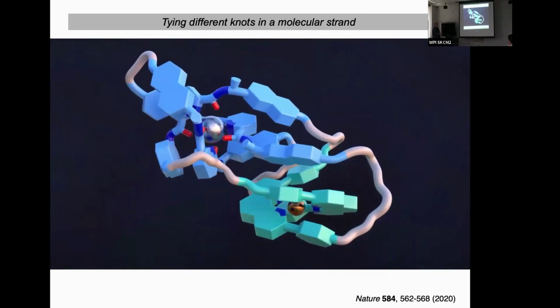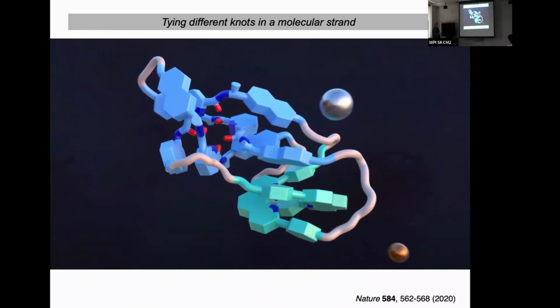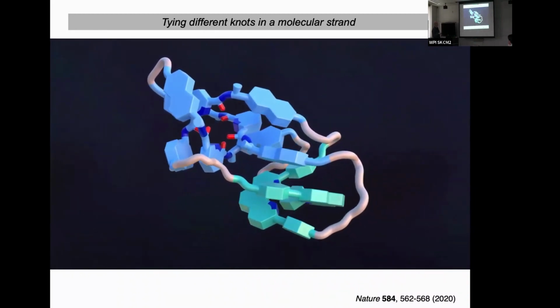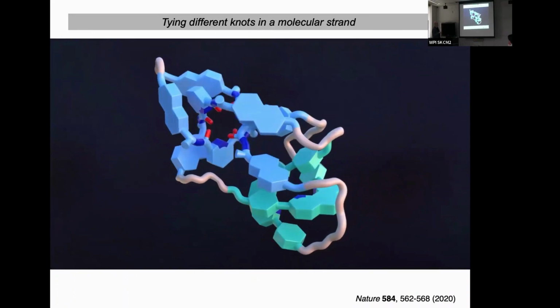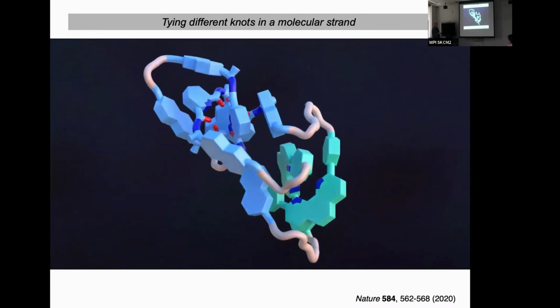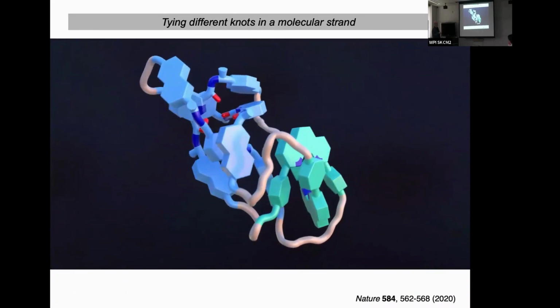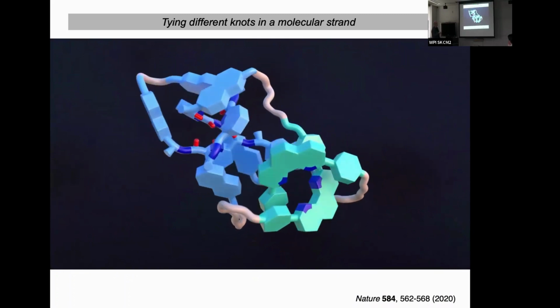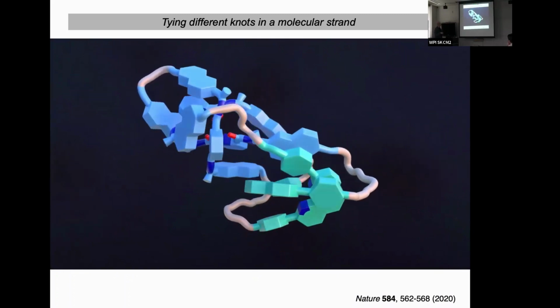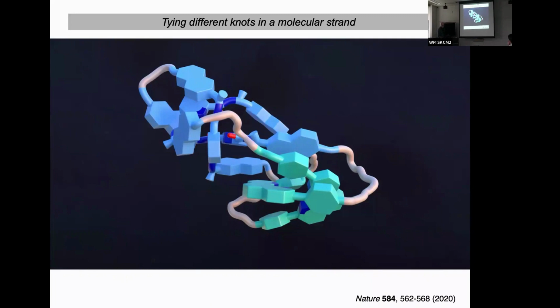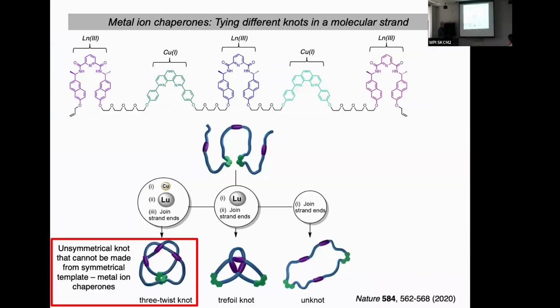We can close the end groups there, then we can remove the metal ions, and we've got a new kind of knot. It's a 5-crossing knot, but it's different to the pentafold knot we saw before. This is a 5-2 knot, rather than the 5-1 knot. So it has a different unsymmetrical kind of geometry that we couldn't make any other way. So this is an unsymmetrical knot. You can't make this from the symmetrical template systems we've been working with before.